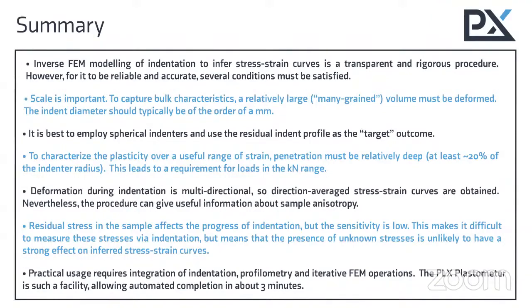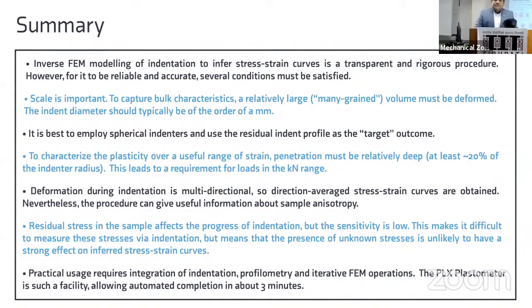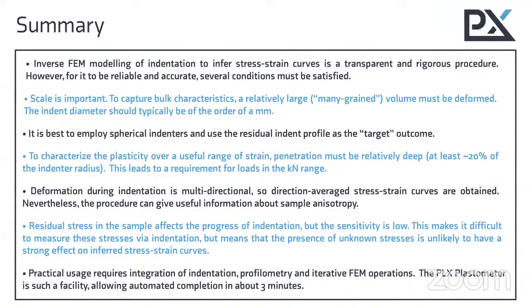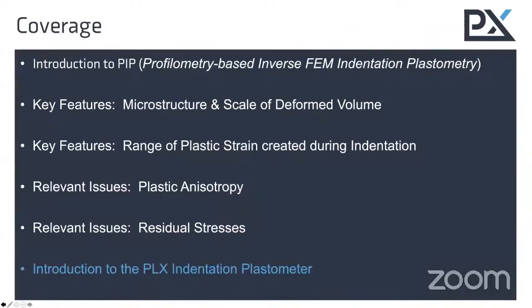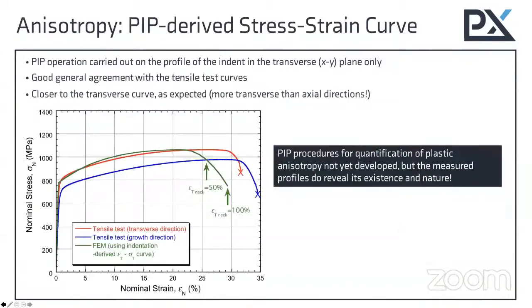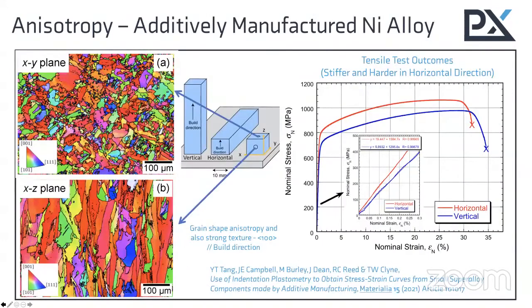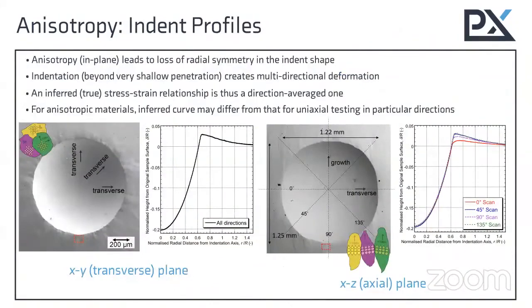Somewhere in the slide you have shown that using EBSD measurement, you have shown the two cross sections, basically two planes of the additively manufactured nickel-based superalloy, and then we are calling it as some kind of texture is present, 100, I guess. And when we are seeing the residual indents, and we are comparing the shape of those indents, is that shape coming because of some crystallographic texture, or is it just the grain morphology which is resulting in this type of shape change?